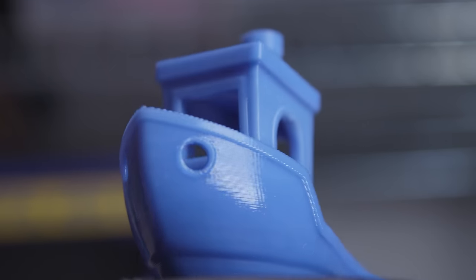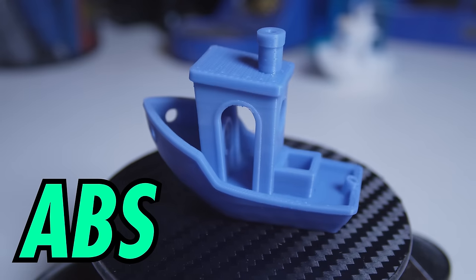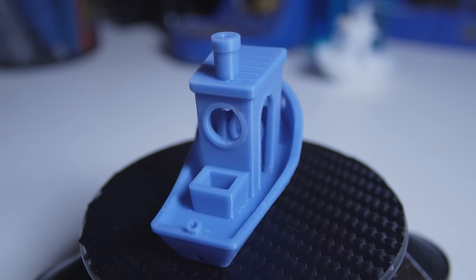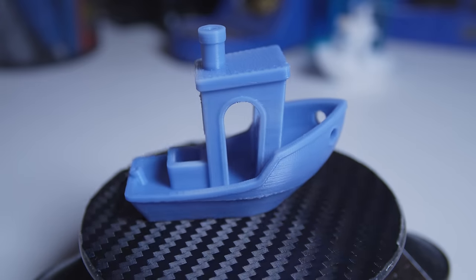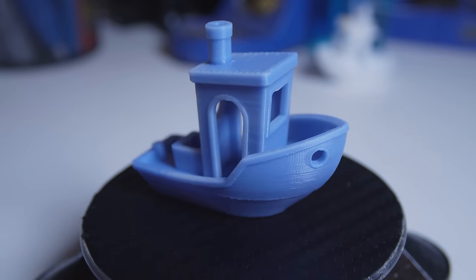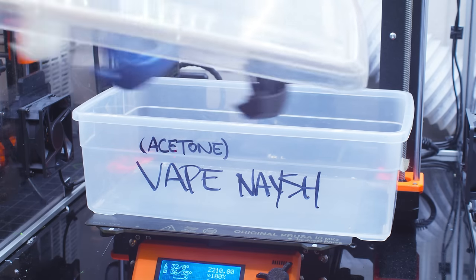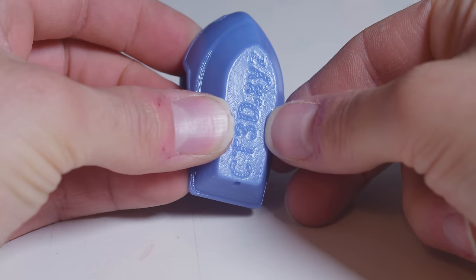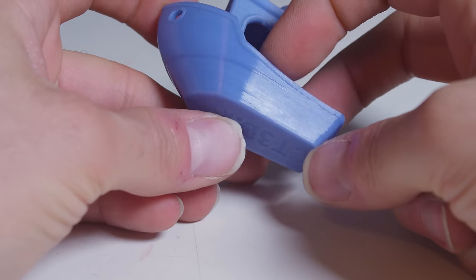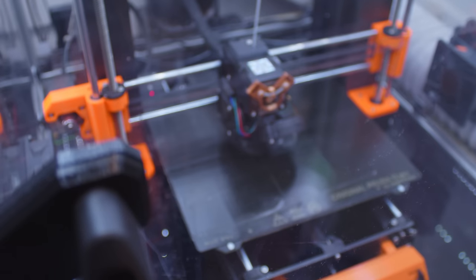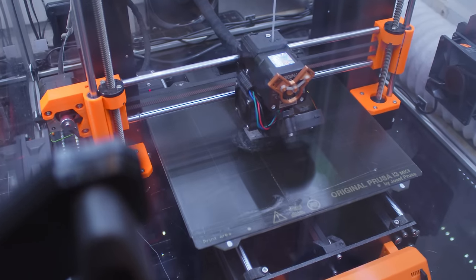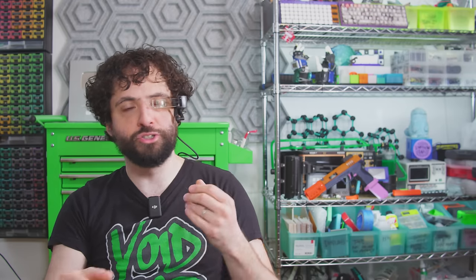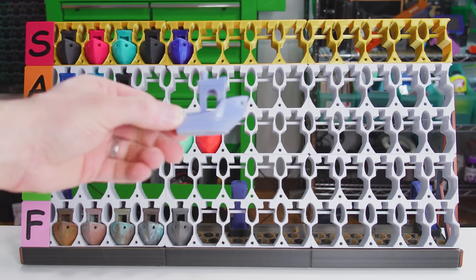Acrylonitrile butadiene styrene is ubiquitous in consumer products, like toys, gadgets, and, until very recently, 3D printing. You can run this stuff amazingly fast, and since it dissolves in acetone, you can solvent weld it and use a vapor chamber to get a seamless surface. ABS is cheap, it withstands some pretty impressive temperatures, and a lot of punishment. It is crazy tough. But ABS has two massive weaknesses, and if you're still listening, you probably already know them. I'll make it quick. It warps like crazy and it reeks. You don't truly need an enclosure to print ABS. It's a bit overblown, but you really want one. ABS is at its best for outdoor prints. It doesn't get too brittle in winter, it doesn't turn to taffy in the summer, and while it's not totally resistant to the sun's ultraviolet rays, it can tank them for most of a decade. But I'm putting ABS in C tier, because if you want these properties, you actually have a better option in the form of ASA.